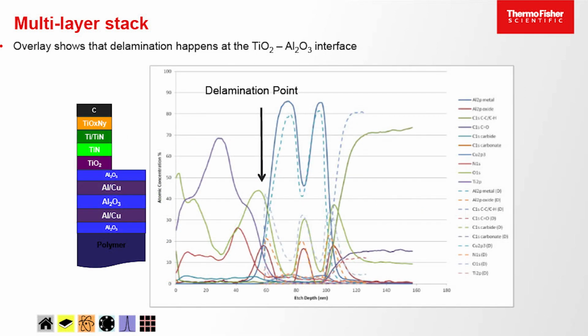And so by putting the two profiles on top of each other, the dotted one is the delaminated area, the intact area is the solid lines, and we can see where the break occurs just by putting them on top of each other. Because we're using the same etch rate, we know that the etch rate through the sample is going to be very similar, and so we can see that this is where the coating is breaking down.